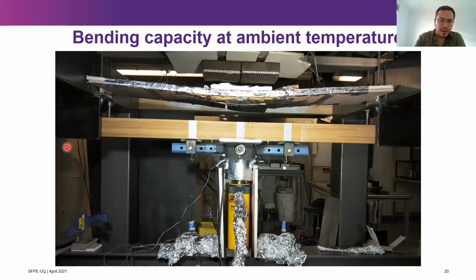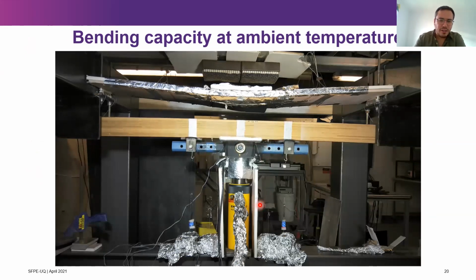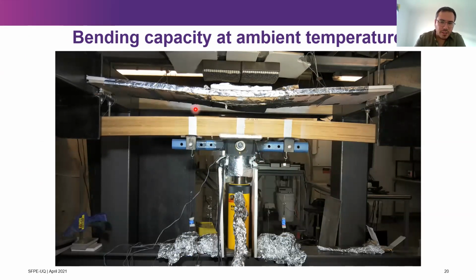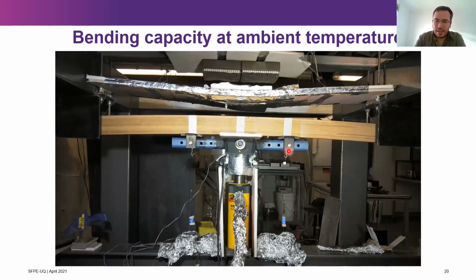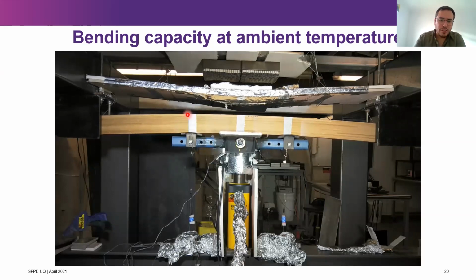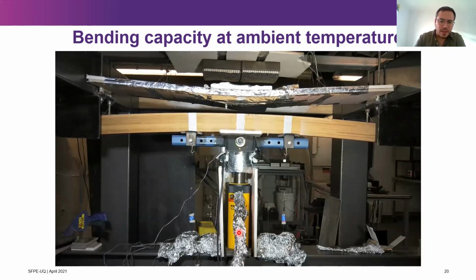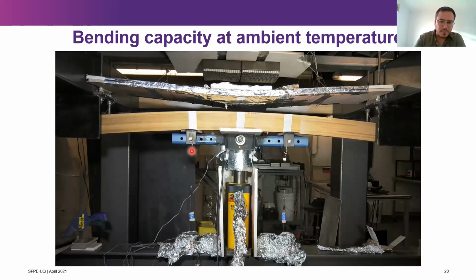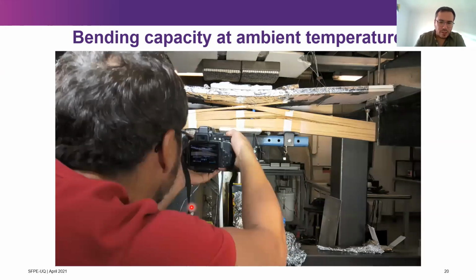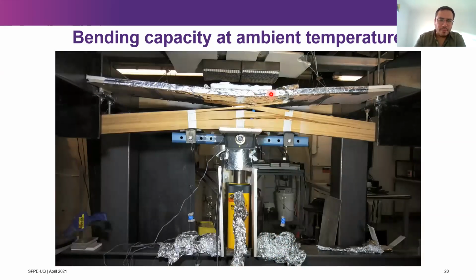This is a video of a test at ambient temperature, so without any fire. So you can see the actuator going up, you see the loading points. We use DIC, digital image correlation system, to be able to track the displacements and the strain, but we also use contact sensors. So we use string pots, and we also use strain gauges. But again, this is a test at ambient temperature, the same test that you usually do when you are applying the load downwards. But again, we wanted to do it here because we needed to apply the external heat flux.